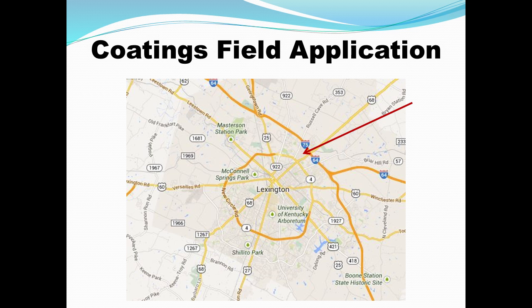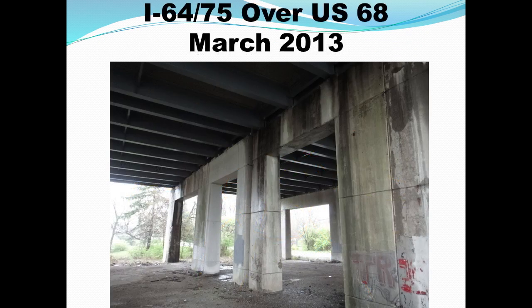We selected a site where Interstate 75 and 64 run concurrent around Lexington, Kentucky, over US 68. This bridge is several spans. I think it is 7 spans, but at the end of the 3rd span is an expansion joint that when we were actually out conducting this work in 2013, I believe it was, when we put these products on, a contractor stopped by and said that he did some work on rehabbing that bridge deck, and that he replaced the joint, and that it had been replaced twice since then, the seals in the joint, because the seals just won't stay in. And as you can see here, we have a lot of evidence of the leaking joint.